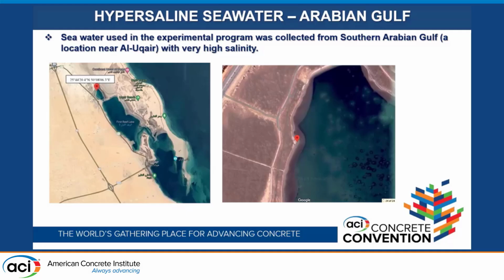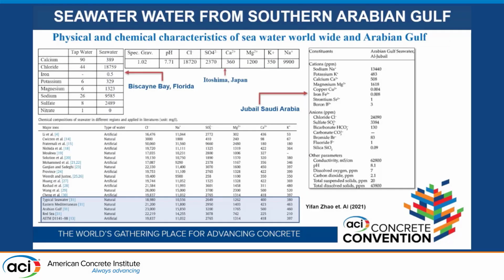This part of the southern Arabian Gulf is very hypersaline, probably because of the lack of water circulation in the Arabian Gulf towards Qatar. If you look at the physical and chemical characteristics of seawater worldwide, typically in Florida, chloride is only 18,750. In Japan, again 18,720, sulfate about 2,370. In most typical seawater, the chloride is about 20,000. In the Arabian Gulf it is more saline, towards the northern side about 24,000 ppm chloride, and in the Red Sea it is 22,219.